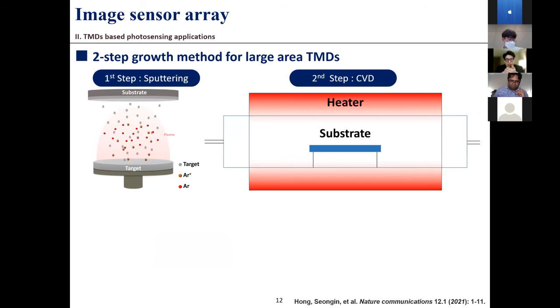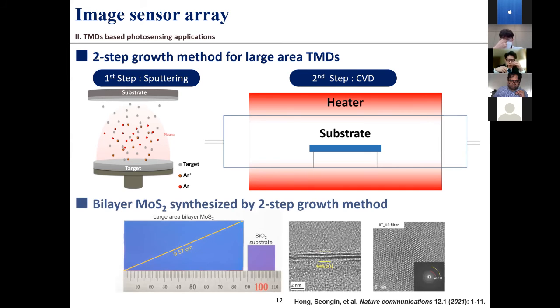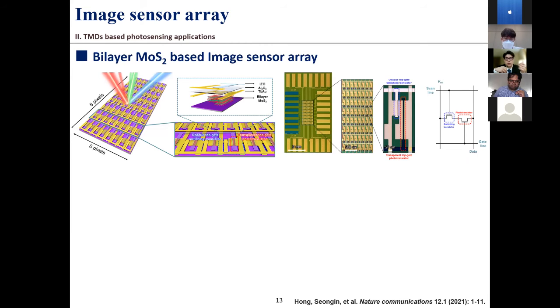The first application is about an image sensor array. We developed a 2-step growth method for large area TMD, which is the deposition of MoS2 using sputtering as the first step, and then sulfurization in CVD as the second step. We could get a large and uniform film. As you can see in the TEM image, this film is bilayer MoS2. Based on this bilayer MoS2, I fabricated an image sensor array.